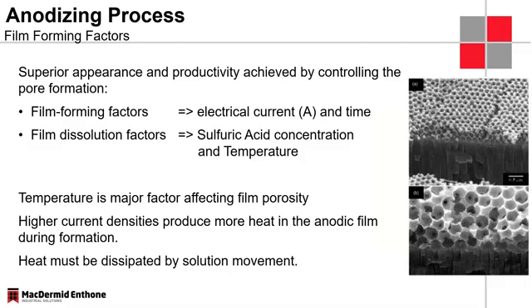So when we anodize a component, there are really two competing actions here. We have on the one hand a film forming reaction, and this is obviously done by the electrical current we pass through the component, and the amount of time we leave these components in the anodizing tank. At the same time, we also dissolve the freshly formed anodized layer, and the parameters or the factors that drive this dissolution reaction are the sulfuric acid concentration and also the temperature.